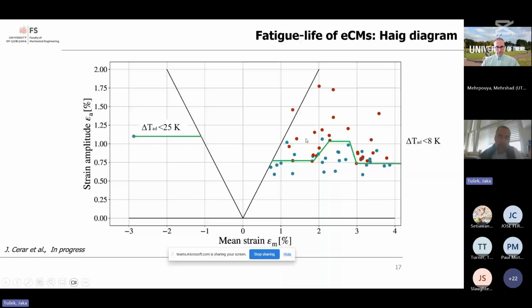As you can see here, in compression, all the samples when cycled over almost the entire transformation plateau survived 1 million cycles, and they have adiabatic temperature changes up to 25 kelvins. Please note that due to asymmetry, the strain to complete the transformation is lower in compression compared to tension. But the strain amplitude is half of the total strain, right?